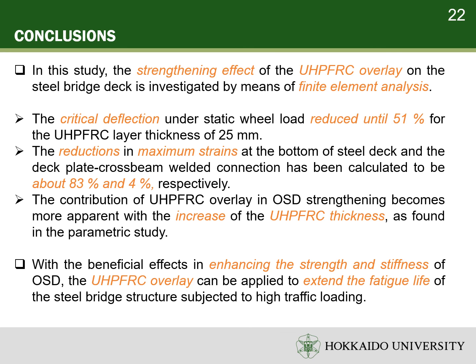The contribution of the UHPFRC overlay in OSD strengthening becomes more apparent with the increase in the UHPFRC thickness, as found in the parametric study. With the beneficial effect in enhancing the strength and stiffness of the OSD, the UHPFRC overlay can be applied to extend the fatigue life of the steel bridge structure subjected to high traffic loading.